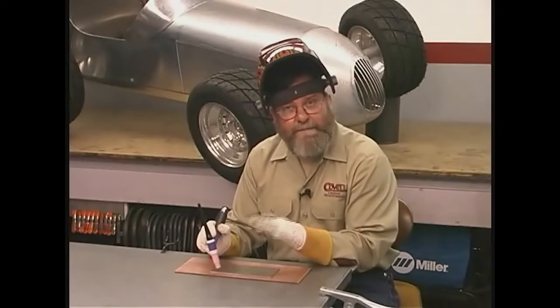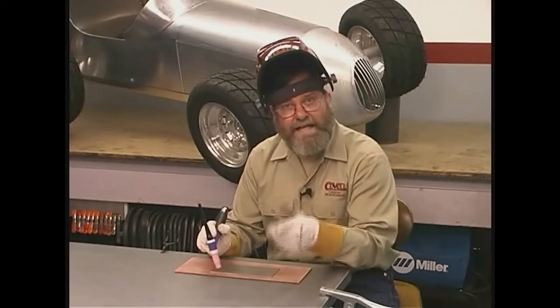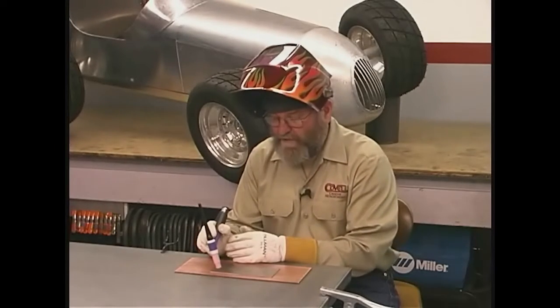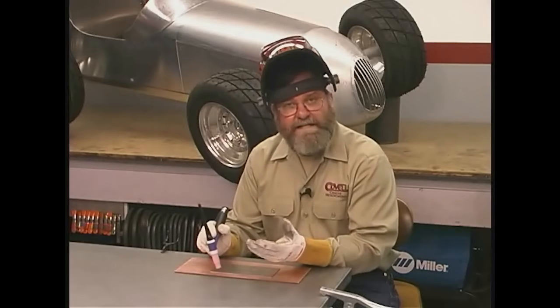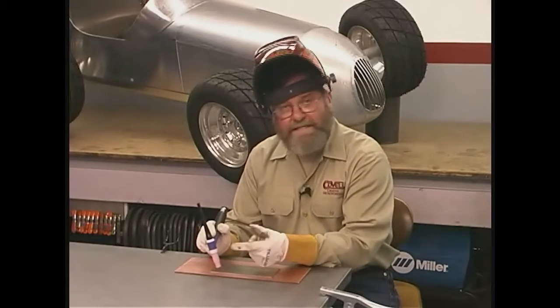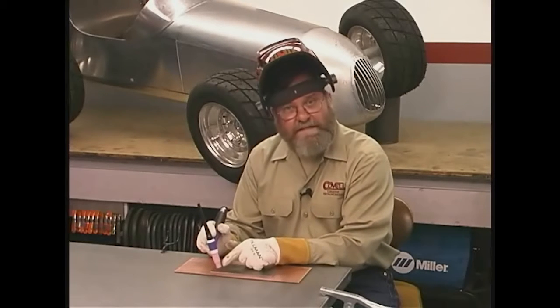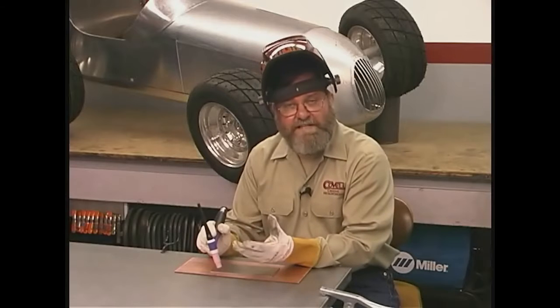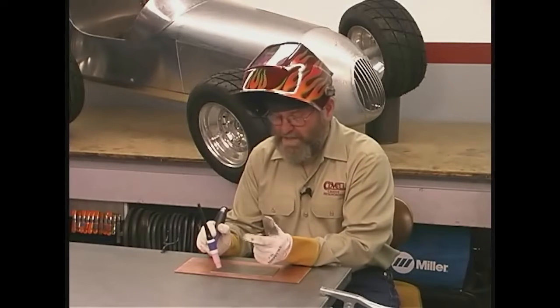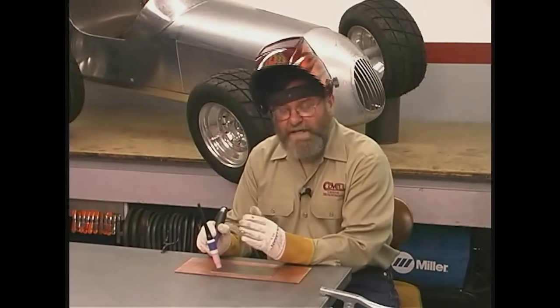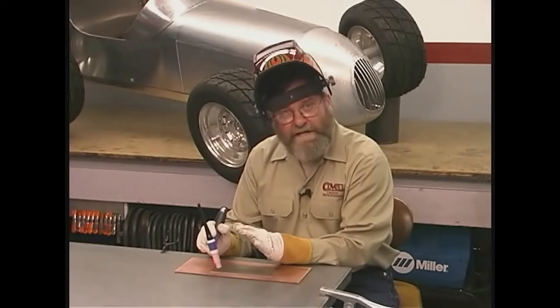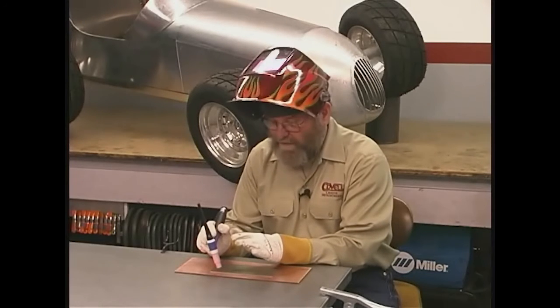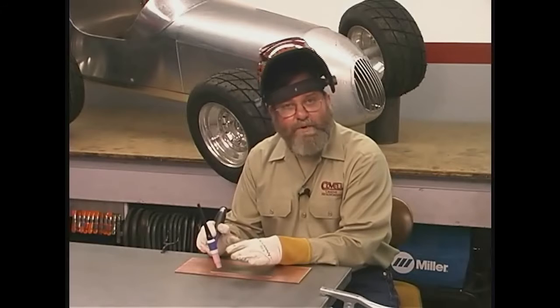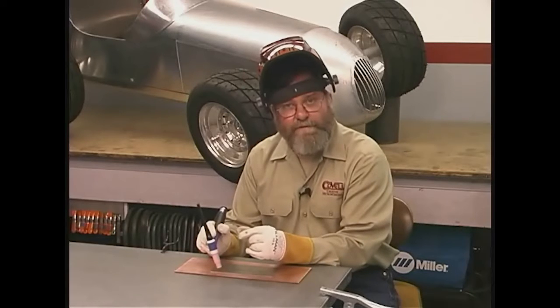Then I tap the foot pedal to get the argon gas flowing. This is very important. This pre-flow will get any moisture out of the gas line that comes to the torch. That kind of moisture could cause weld contamination. And it also makes sure that the tungsten electrode is shielded with gas when the arc starts. Once I have the pre-flow going, then I start pushing the pedal down to start the arc. And as I push the pedal down more and more, a puddle will form.